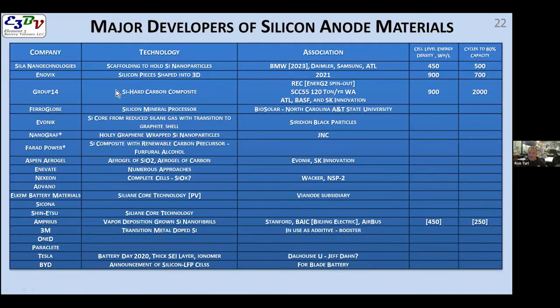The silicon expands, and all these companies that you see here are developing methods to keep the silicon from over expanding, because when it does, it's brittle. Lithium goes in like a sponge, expands the silicon, but it's not a sponge, it breaks apart. And as it does, it creates all this extra surface area, all these passivation layers form on it. There's a lot of interesting things that go on just from the electrochemistry plus the physical chemistry, and the electrolytes can be modified to help accommodate this as well.